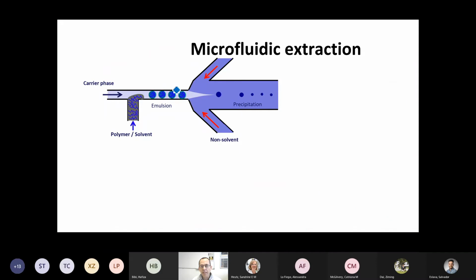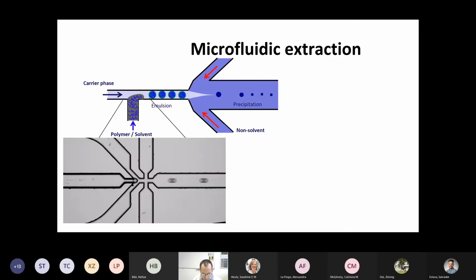And the trick that we play is that we then immerse this into a fluid that is selective to the solvent that is within the droplet, and it's going to suck that solvent out, a bit like if you left, say, an apple and you go on holidays, that apple dries and crumples. We're going to do the same thing, but instead of drying in air, we dry it within another solvent. And so this will be familiar to many of you.